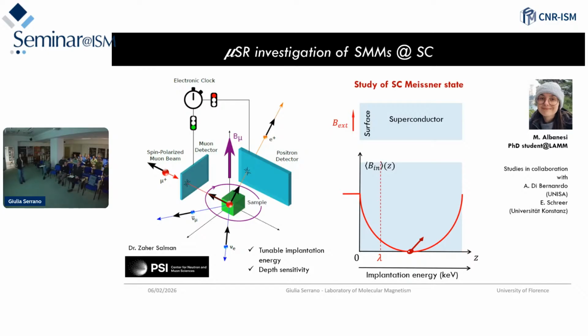So this technique is usually used to probe, as a function of the muon implantation energy, which scales from the surface towards the center of the bulk, the depth profile of the internal magnetic field of the superconductor, that from the edge, thanks to the Meissner state, must decay towards zero when you go in the bulk.